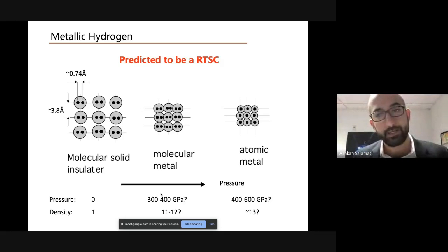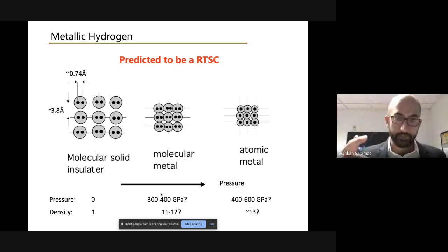What's important about metallic hydrogen is that it's predicted to be a room temperature superconductor. So we were working on metallic hydrogen. We knew it was predicted to have these remarkable properties. We also knew that the pressures you had to get to were just so high that the kind of measurements we were interested in would be impossible. And so we were like, okay, we know metallic hydrogen does this. We know hydrogen sulfide also shows remarkable properties. Can we find a way to merge these ideas together and achieve room temperature superconductivity, but at a much more modest pressure?